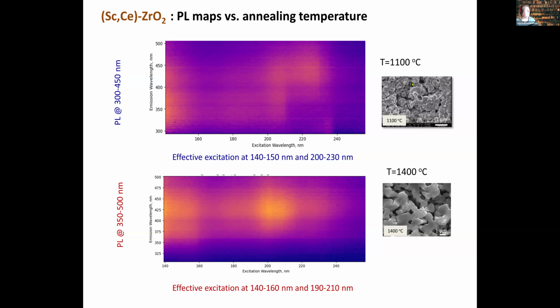On these maps, for the sample annealed at higher temperature, we have brighter emission, which appears from 350 to 500 nanometers and is excited mainly from 140 to 160 nanometers and around 210 nanometers. For the samples annealed at low temperatures, we have a nearly similar picture, but the photoluminescence band is shifted to lower wavelengths, and the excitation band is shifted to higher excitation wavelengths.